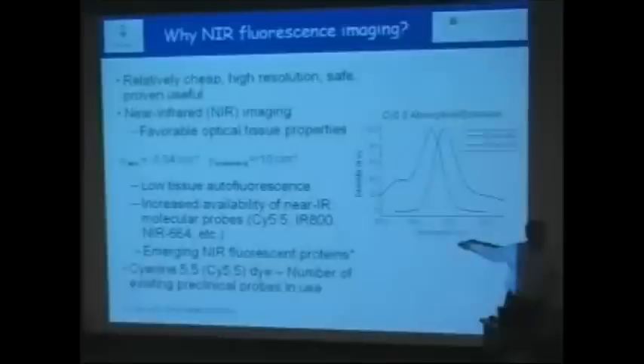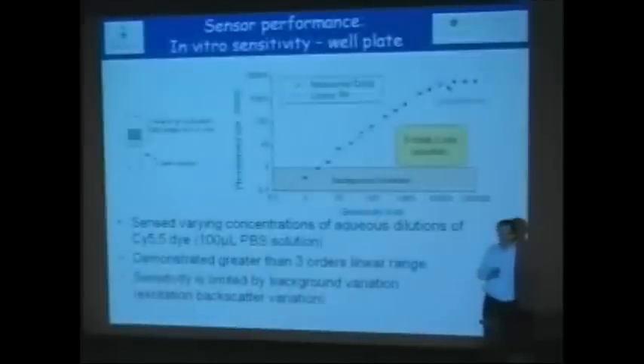Most of what you lose is due to scattering. If it's scattering, you could penetrate a millimeter into tissue, and this is very easy to collect afterwards. At the same time, the autofluorescence, the natural ability of the body to create fluorescence, which is the background you would like not to see, is rather low. In comparison to the visible, where you could see glowing mice that are glowing in the green, this doesn't happen. So these are part of the advantages of why we chose Cy5 dyes.